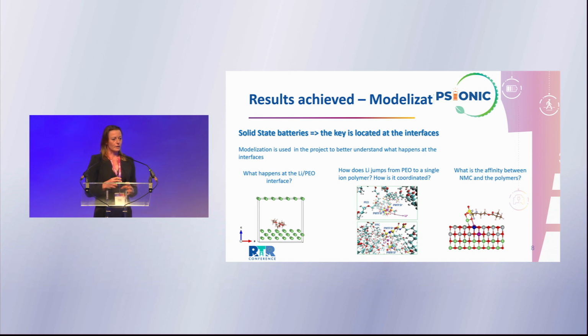We also try to understand the compatibilities and the interactions between the different polymers we will put in the battery. How the PEO transfers its lithium to other polymers, to single-ion polymers that are integrated in the cathode side. And we also try to understand why the active material is more or less compatible with the different polymers. In theory, it's compatible, but in the process, we see that there is not a very good dispersion. Why is it happening? Modelization helps us to understand and then go to the lab and try to find solutions.